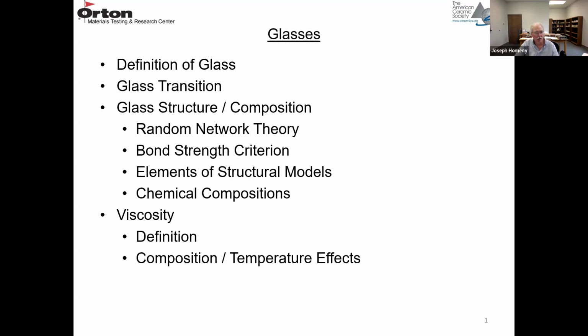So I put a lecture in here on glasses. If there's a small amount of glass present, it's usually at the grain boundaries. If there's a large amount of glass present, you can consider it a second phase. And if you have as much as 30% glass present, that's the point where you lose structural integrity at high temperatures. So any glass present tends to lower hot strength, it lowers creep resistance, and there's usually some amount of silicate glass present in refractories, especially in the alumina silica refractories and then some of the basic refractories, especially if there's a chrome type material present.